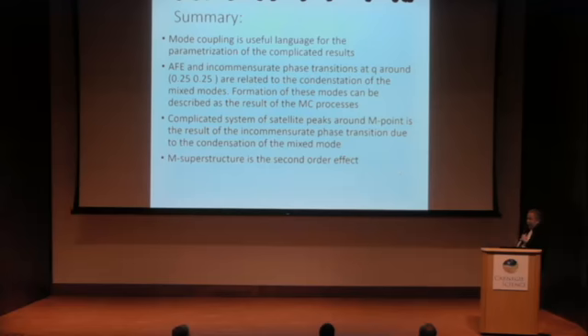Well, I believe I once answered your question. It was in San Antonio. It was a slightly previous version, so this one is modified. There is a modification to the phase diagram in the sense that the intermediate phase is definitely not rhombohedral. So it's still ferroelectric, but it's definitely not rhombohedral. That's one point. The other is that we can see a very narrow region of existence of an incommensurate phase with an incommensurate wave vector of about 0.18, something like this. That's a weak modification.